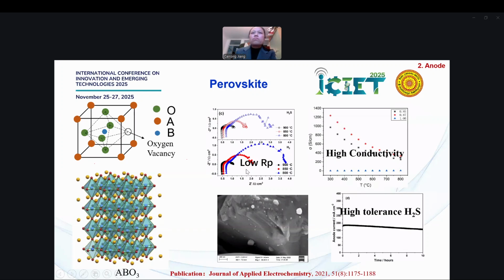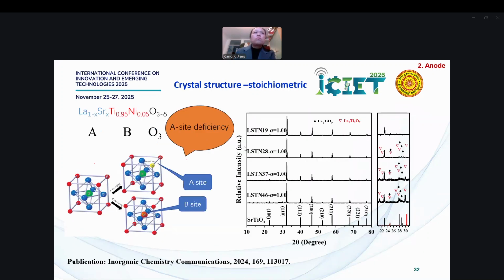But the poor thing is it always gives high resistance, meaning low polarization activity, so these cells do not have a good catalyst. So we have to try to improve it. The first thing we think about is the whole structure: we have an ABO3, and it's quite flexible. For the A site, we can use all sorts of ions like lanthanum, strontium, and for the B site, we can choose titanium and nickel. With this variability, we can dope nickel at the B site, and in the future, because we found a way to make it exsolve as nanoparticles, we give a better catalytic activity. But in the beginning, we didn't know.